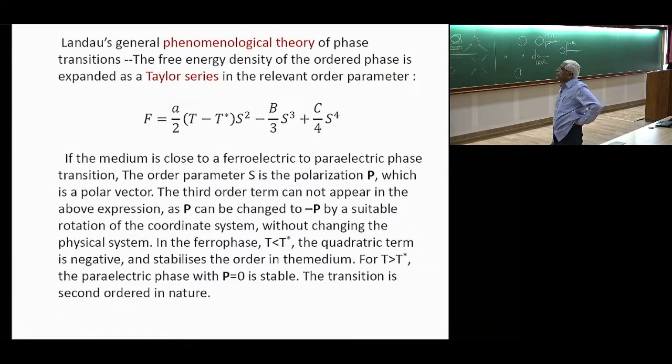And the other approach normally that one uses for studying phase transitions is the Landau phenomenological theory. So you just use the fact that there is a broken symmetry here. Here, in the particular case of nematic, it's a broken orientational symmetry. But in general, close to a second order phase transition, you can always write a Taylor series expansion of the free energy. S can be anything, supposing it is, in fact, a ferroelectric polarization.